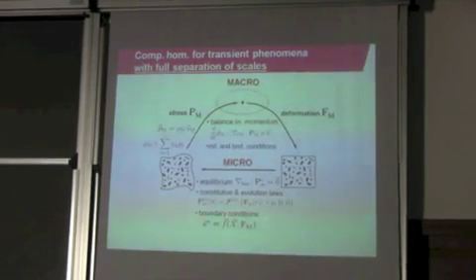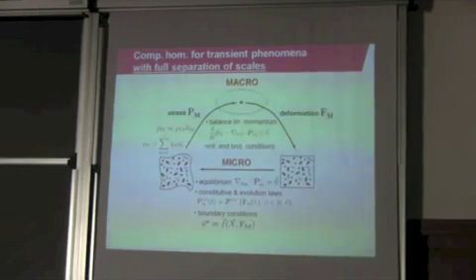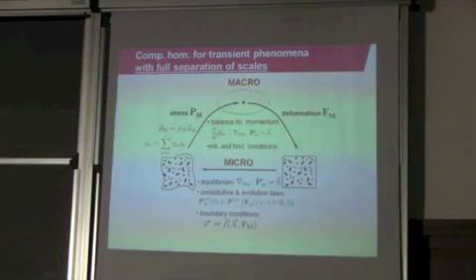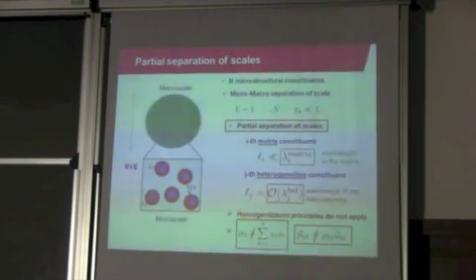Now if you look at these local resonance materials, among other homogenization techniques, the computational homogenization technique has also been applied by many people. I don't even put references here, it would be too much. The quasi-static case has been done an enormous number of times, and also for dynamic cases. But note importantly that even if this is applied to the dynamic case, on the macroscopic scale the balance of linear momentum is solved, while the microstructure is assumed to be in equilibrium, in a steady state condition. The microstructural computation then merely serves as a constitutive box, giving the stress-strain relation to be entered in the linear momentum, and the momentum expression is in fact a trivial statement. Now if you look at the local resonant metamaterials, there is one principal difference.